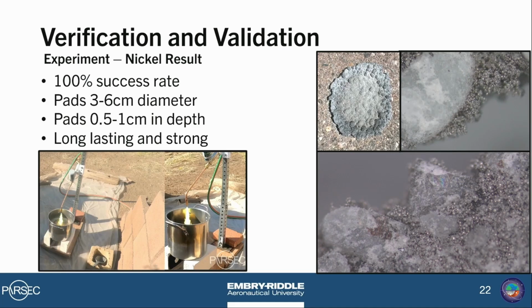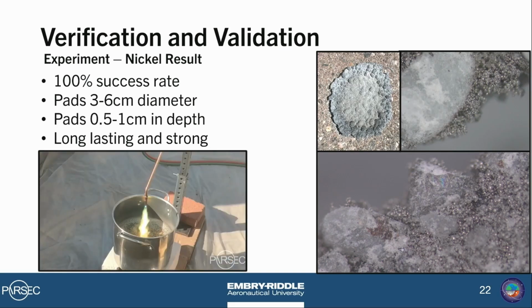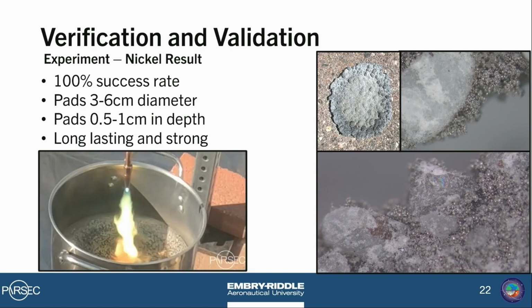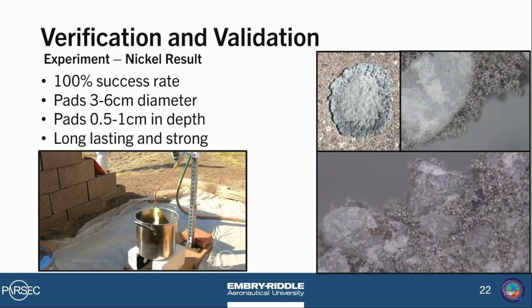On the right-hand side, we can see the results from our 60-second duration test, which is also what the video is playing there. This test yielded a pad that is approximately 6 centimeters in diameter and about half of a centimeter in depth. The pad itself has fairly high strength, especially compared to the alumina tests. Additionally, supported by the fact that we have it here with us today, along with a few other samples, and they will be out at our poster session if you would like to come see them.